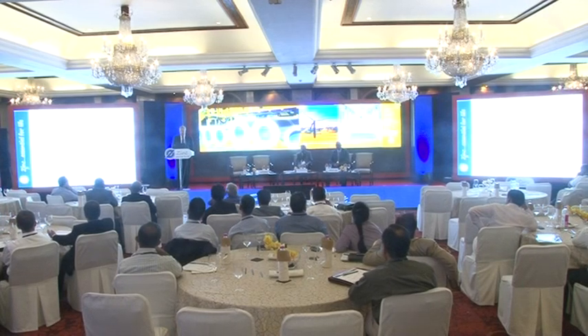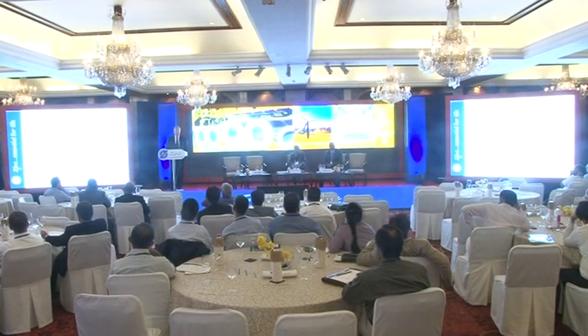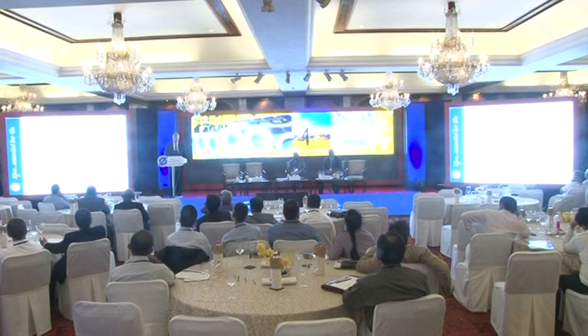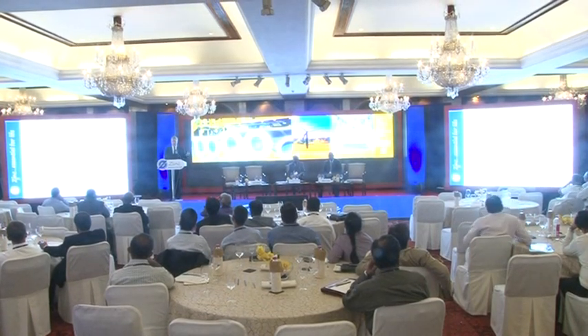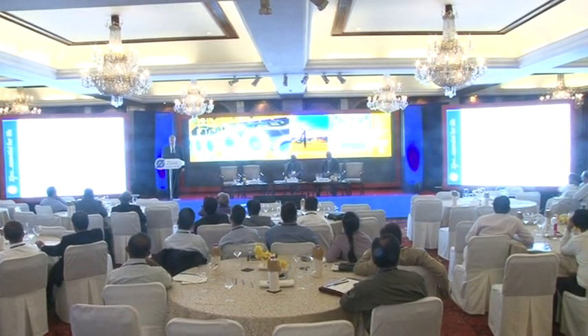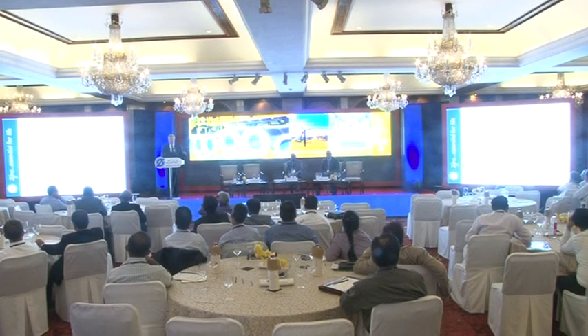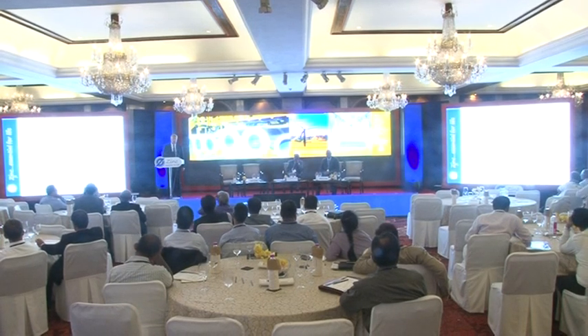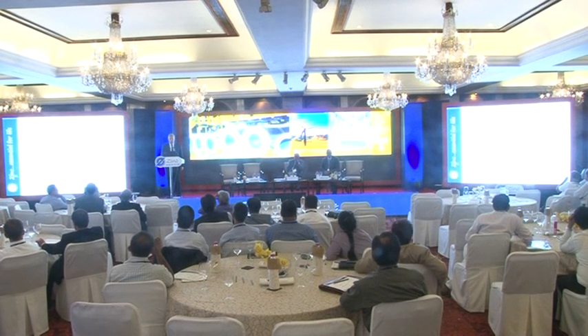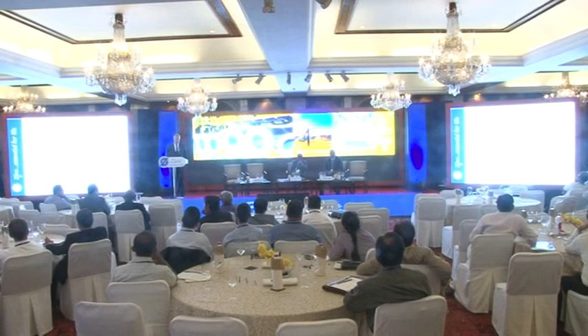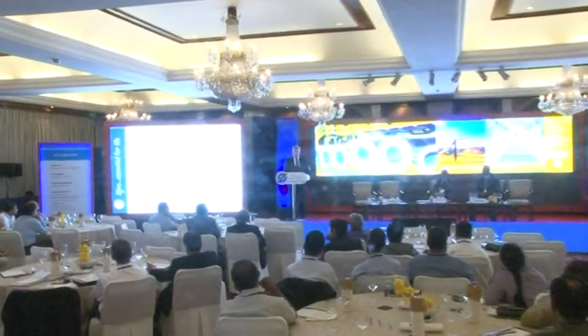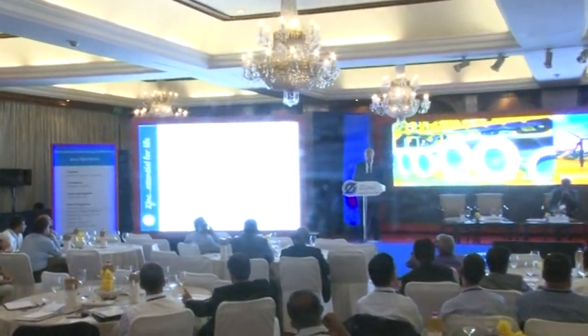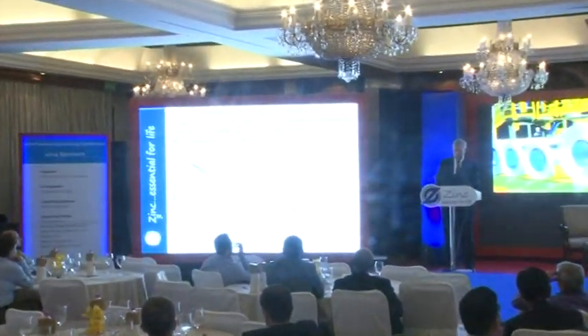So this shows the sorts of things that are involved metallurgically. We won't spend any time on this, just to show that the different cooling rates we get, which are these diagonal temperature versus time lines, as you cool down with different cooling rates, you end up in different metallurgical phases with different strengths. And so by controlling our cooling rate, we can end up with a wide variety of metallurgical structures. And this is one of the beautiful things about steel, is that you've such a wide range of endpoints for processing here with these different cooling rates.